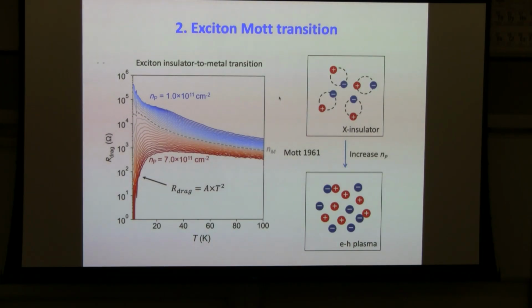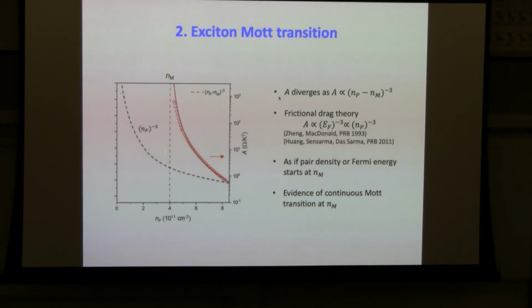I think, because of the perfect Coulomb drag data, you do expect that there is a transition from this to that, because you go from with excitons to without excitons. But what's a little bit surprising is that this scaling coefficient, this A coefficient here, would actually scale and diverge at the Mott density in a way that looks like there's a quantum critical point at the Mott density. Yeah. Okay. All right.